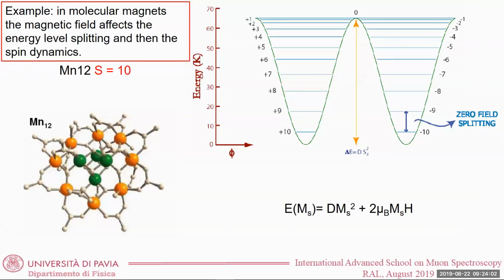For example, if we go back to our manganese 12 molecular magnet, what we have is that if you do not apply an external magnetic field, you have a splitting of the levels, which can be labeled by the Z component along the anisotropy axis of the spin S equal 10, and this splitting is associated with the magnetic anisotropy. So basically, in zero field, you have just this term, and so you have ms plus 10, minus 10, minus 9, plus 9, and so on. Now, if you want to study the dynamics of this system, you know that if you apply a magnetic field, you will induce a Zeeman splitting of these levels, and so the energy level splitting will change because of this term.